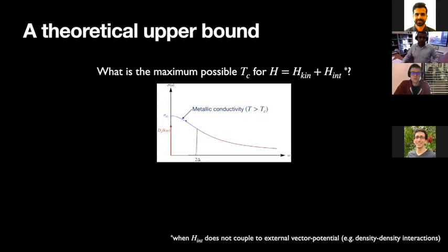So the question is, all of this missing spectral weight, where does that go? That precisely goes into a delta function at 0 frequency. And the magnitude of that delta function is precisely this phase ordering scale that I was talking about. So in this picture, ds would be basically given by the area of this portion of the curve.